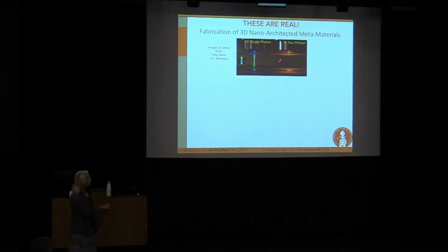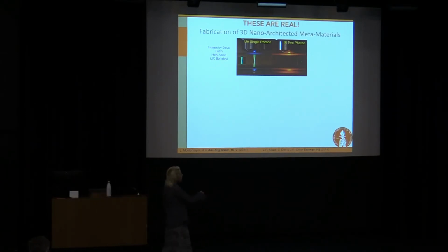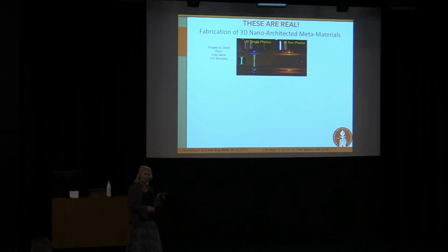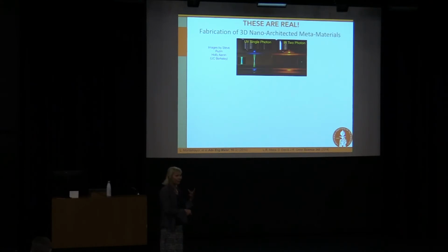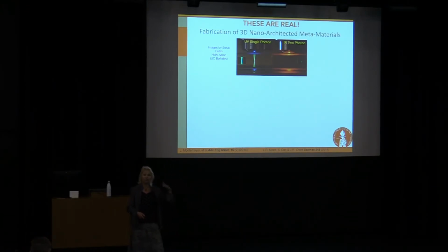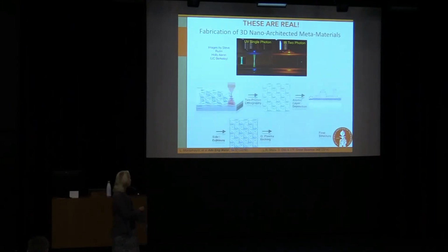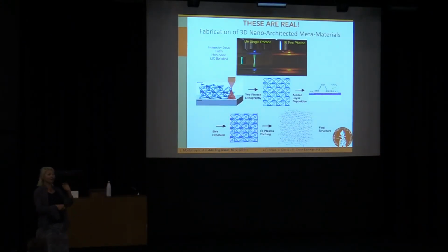So instead of using UV lithography, which is I think what many people use here to define two-dimensional features, we use something that's called two-photon lithography, using a less powerful laser. But we flood the space with a lot of photons. And so the constructive interference of two photons in a single laser pulse produces a sufficient amount of power to cross-link the polymer in that voxel. So what you see here is this tiny little voxel, so that allows us to eliminate these diffractive cones of the UV light. So less powerful laser, but a lot more photons. And so this two-photon lithography technique allows us to then sculpt whatever complex shape we want.